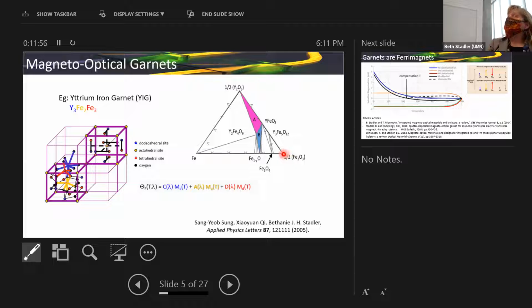But it turns out I found this phase diagram when I could not explain why, depending on how we anneal the garnet, we would get all these different phases. So way back in 2005, it turns out I might get this perovskite, Bixbyite, and this orthorhombic phase, but I wouldn't even see garnet.